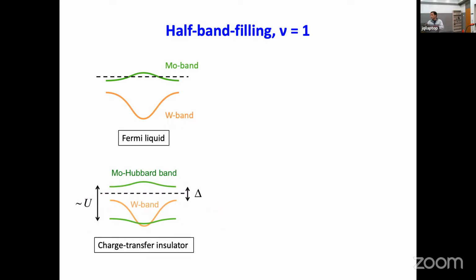But your electric field can also bring the tungsten band closer, right? And in fact, you can reduce the charge gap to be smaller than U. Then it's a charge transfer insulator in this case, where the charge excitation is from the lower Hubbard band of the Moiré to the tungsten selenide Moiré bands.